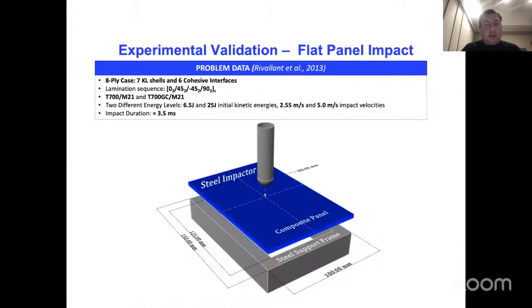Okay, so let me take you through some experimental validation. This is a flat panel impact. This is a famous paper from Rivallant et al., 2013. This is an 8-ply case. Here's the lamination sequence: 0 repeated twice, 45 repeated twice, negative 45 twice, 90 twice, symmetrized. And so what we're doing, the plies with the same fiber orientation are grouped together. We're going to impact them at 2 different energy levels, 6.5 and 25 joules. The impact duration is about 3.5 milliseconds.